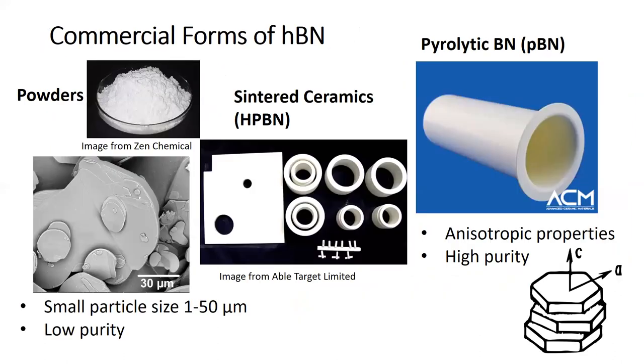There are essentially three commercial forms. There are powders, with a typical powder size of maybe 1 to 50 microns across, which look something like this. These tend to be low purity because they have lots of native oxides on the surface. You can take the powders, press them into ceramics, and sinter them. This is the hot pressed boron nitride form. It's a very soft material, so it's easy to machine.